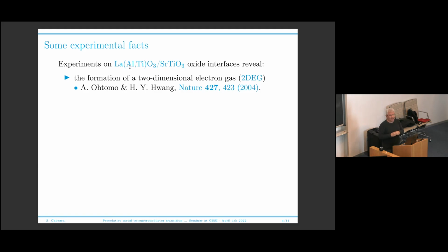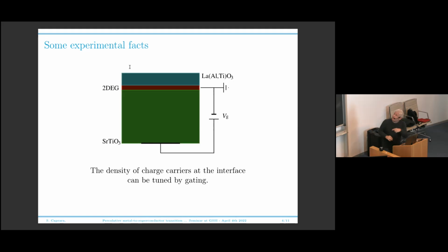This is a very striking result because you take two insulators, you join them, and at the interface, you form a two-dimensional electron gas, which is really two-dimensional. The thickness of this two-dimensional electron gas was measured to be a few nanometers. So it's really a very two-dimensional electron gas. So this is more or less the situation. You have lanthanum aluminate or lanthanum titanate on top. Then you have the two-dimensional electron gas, and then you have bulk strontium titanate.